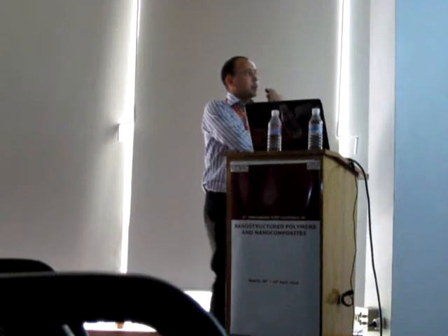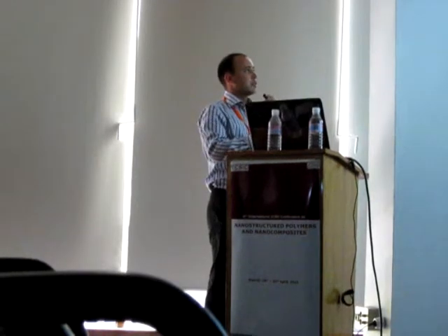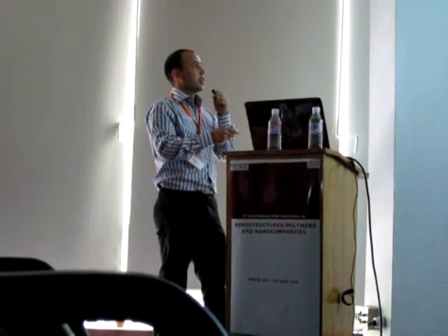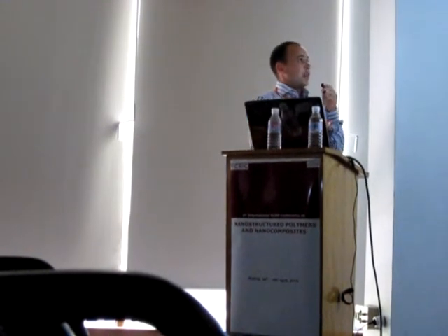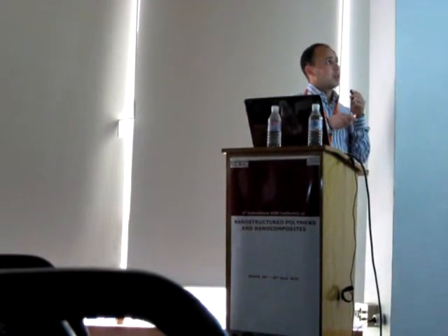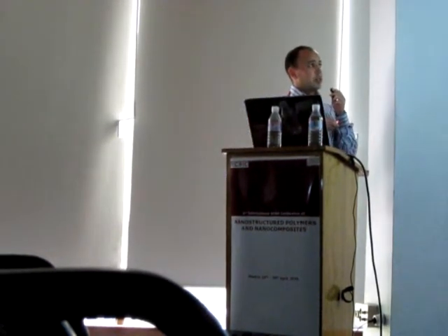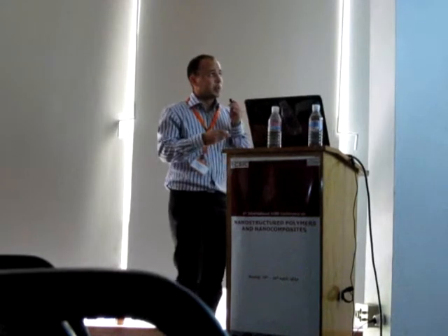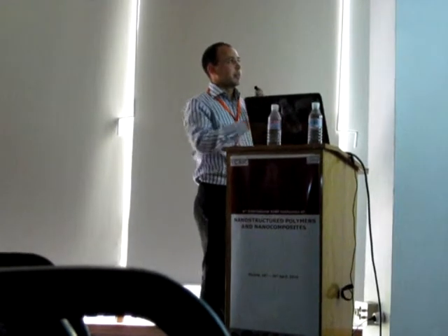For example, here we model the conversion rate at different positions in the extruder as a function of feed rate. So we remarked that when feed rate increases, conversion rate decreases. These results can be explained by this figure. Here we present the variation of residence time as a function of feed rate. So we note that when feed rate increases, the residence time decreases, and we know that conversion is related to the residence time, and then we can explain this behavior.